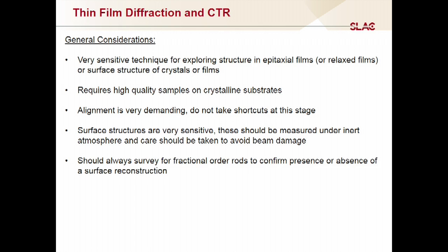But it is very sensitive. It is so sensitive that you should be very careful about the conditions that you do the measurement in. It's not unheard of that simply by putting the X-rays on your sample, you've changed the surface, especially if it is in the presence of water or oxygen. So you want to think carefully about that and make sure that by doing the measurement, you're not changing the thing that you want to measure. And always make sure you go and look for those fractional rods because there may be a surface reconstruction. You want to make sure that you don't miss it.